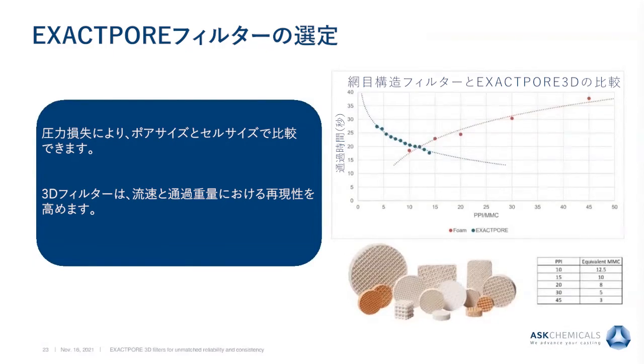PPI and MMC have an inverse relationship. If you increase the number of PPI, you decrease the size of the cell. With MMC, as you increase the number of MMC, you increase the size of the cell. The right side chart shows a pressure drop comparison of pore size versus cell size, which equates very similarly to